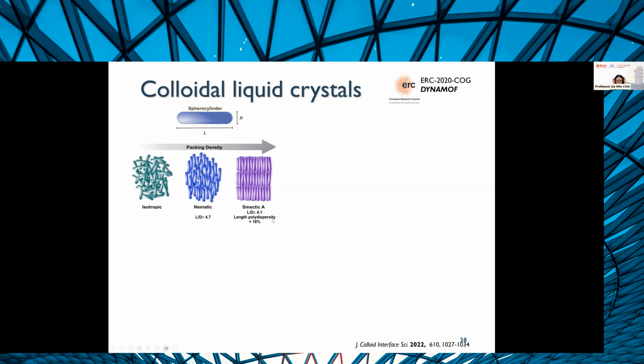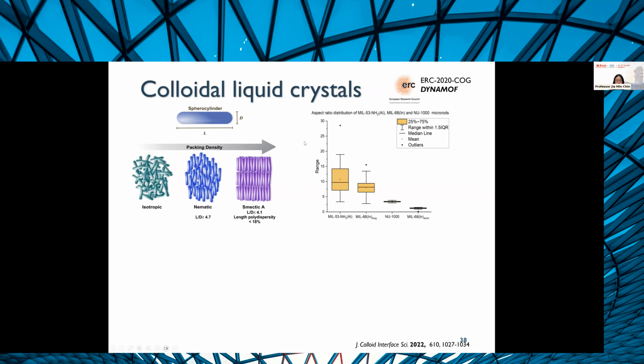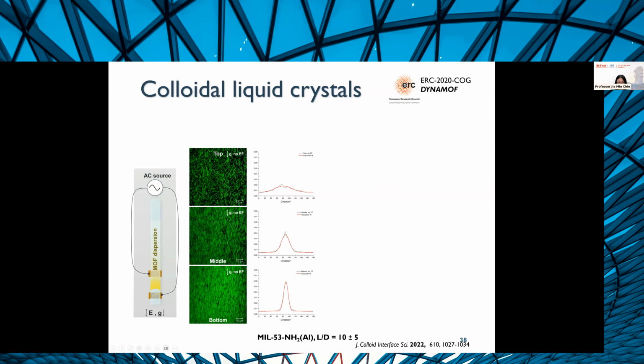Now, some of you might be looking at this and thinking, hang on, most MOFs don't have aspect ratios that are quite this high. So what do we do then? We thought, maybe we could cheat a little bit and exploit packing interactions together with electric fields to apply this kind of packing to crystals that have low aspect ratios, lower than this minimum of 4.7. So what we did was synthesize a bunch of different types of MOFs with different aspect ratios, ranging from about 10, very polydisperse, to about 1.2, which was a little bit more monodisperse. And starting with the MOFs with the highest aspect ratio, amino MIL-53 in this case, we then